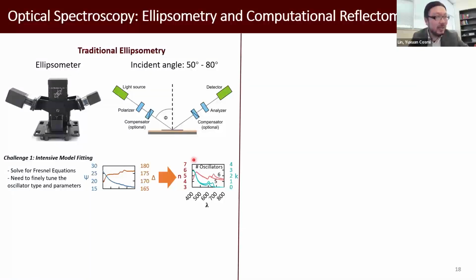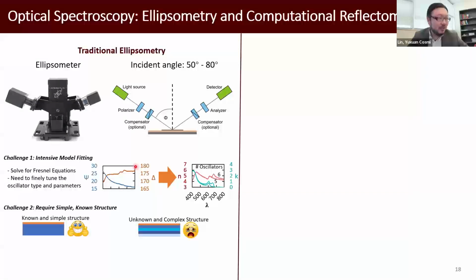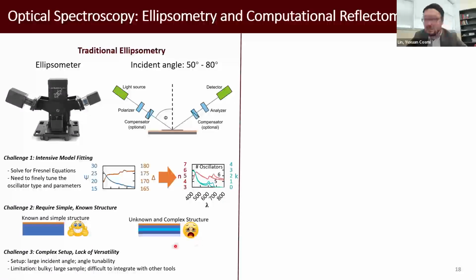This system, I would say, is very convenient, but not powerful enough. The first challenge is it requires intensive model fitting. You need to have some prior knowledge about the material to be detected. And if the substrate is more complicated, it's going to be impossible to fit the data to the model to get the extraction. So if we have an unknown and complicated underlying substrate, you put a film on top, it's going to be impossible to use ellipsometry to figure out the refractive index.